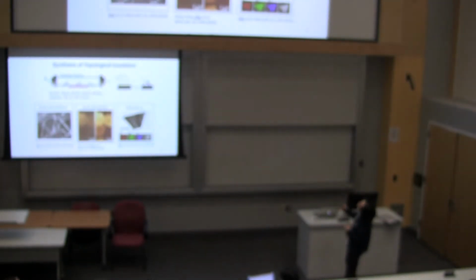Okay, so this method is quite versatile. You can grow quite a number of different topological materials this way: bismuth selenide, bismuth telluride. Now, if you don't use metal particles, because these are layer structures, you're going to do a physical vapor to solid deposition on the growth substrate.